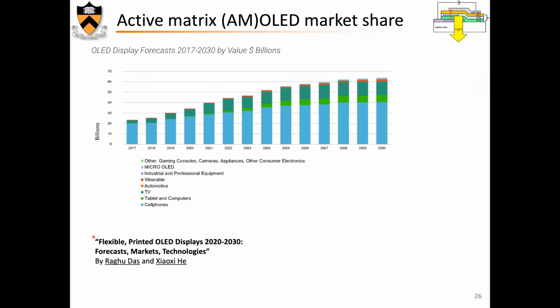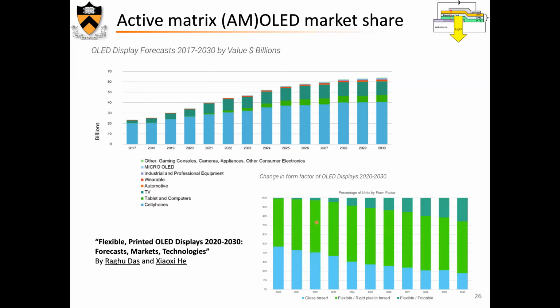And if you look at the market over the next few years, it's quite considerable. The displays in cell phones up to $40 billion. The dark green here are the televisions, and so on. So it's really increasing steadily. And another interesting thing is the substrate. In blue here, you have the glass-based substrate, and this is where we are now, 40% or so, and in 2030 will be down to 15% or so, which means that the flexible and the plastic substrate are going to take over on all these applications.